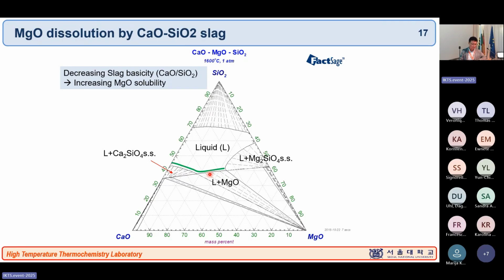Okay, so for example, if you have a slag like CaO-SiO2 50-50, and you put this into the MgO refractory, then magnesium oxide can be dissolved continuously until it reaches this boundary liquid composition. So this is the MgO solubility in your slag. And so in order to design your slag properly to minimize your MgO refractory dissolution, you have to take this composition for your slag composition. Of course, depending on the refining capacity of your slag for steelmaking and MgO together, the best one is this dicalcium silicate and MgO co-saturation point.